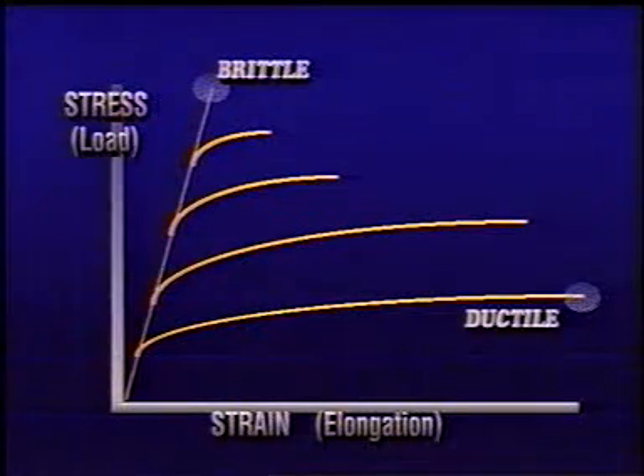During manufacturing, ductile metals can be subjected to extensive forming operations, such as bending, stretching, compressing, twisting, and deep drawing, without rupture or cracking. Brittle metals, on the other hand, are likely to break with this kind of treatment. Very hard steels and gray cast iron will crack or fracture without showing any significant plastic deformation in such cases.